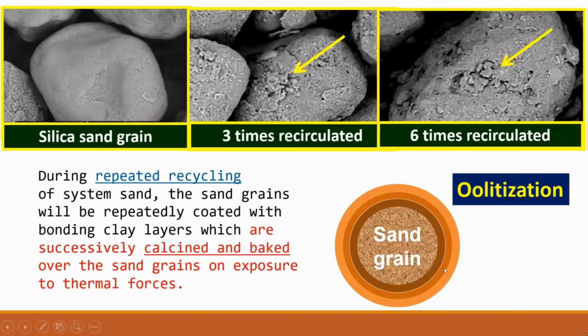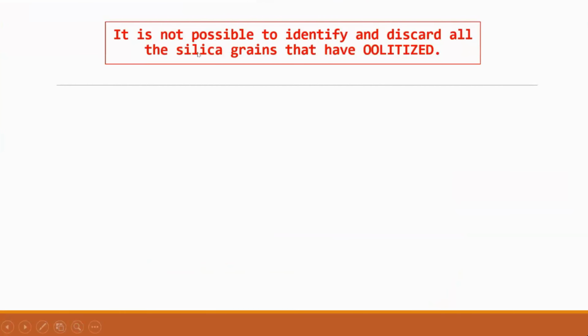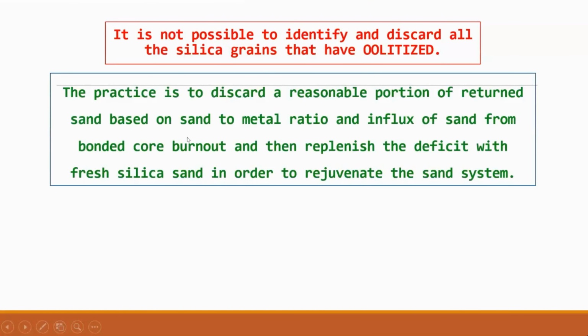Now the problem is these oolitics cannot be seen or cannot be separated in an easy way because they are all mixed up. They don't have too much of density difference where you can employ some differential separation techniques. So it is not possible, and the quantity is so small, but they are significant. So it is not possible to identify and discard all the silica sand grains that are oolitized. So what is done? The practice is to discard a reasonable portion of the returned sand based on sand to metal ratio, which will decide how much of the oolitization is going to take place. And the influx of sand from bonded core burnout.